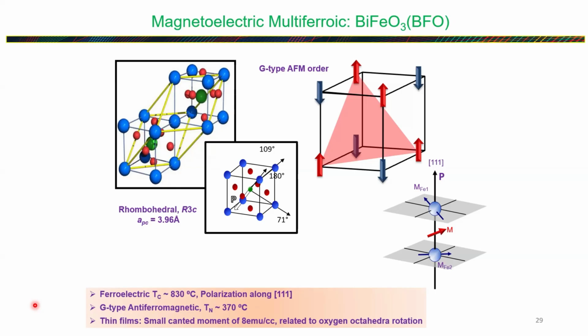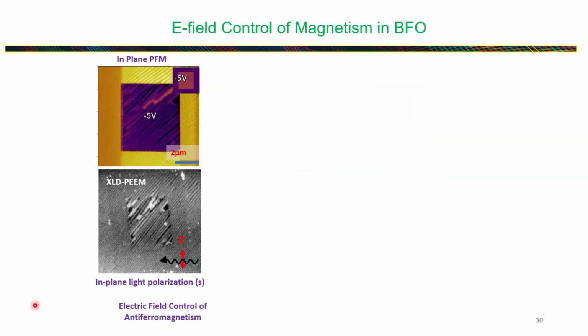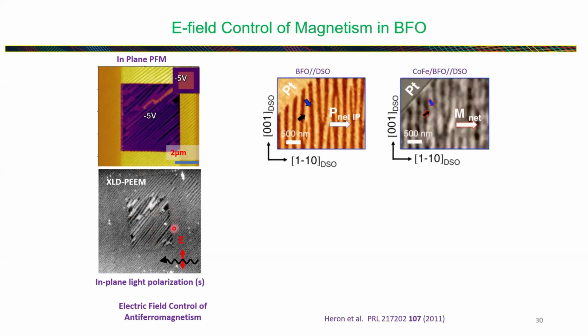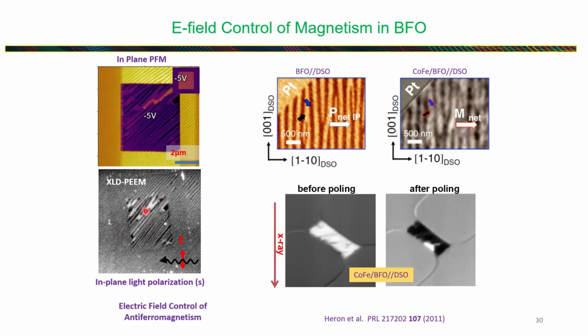Okay, so when you apply the electric field and you map the ferroelectric polarizations, what you see is that there's a domain. Basically, this is a ferroelectric domain. Okay, and then you also map the antiferromagnetic domain by XLD PEEM. What we see is that there's a one-to-one correlation between the ferroelectric and antiferromagnetic domain. Interestingly, when you put a ferromagnet on top of this, for example cobalt iron, this ferromagnet does mimic exactly the domain that you see here in XMLD PEEM. And then when you apply the electric field, you can basically pole them, and then you can switch them from white to black with electric field.